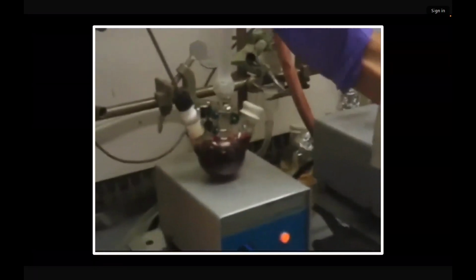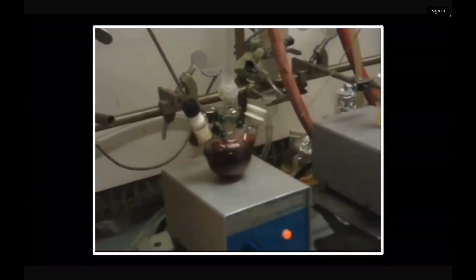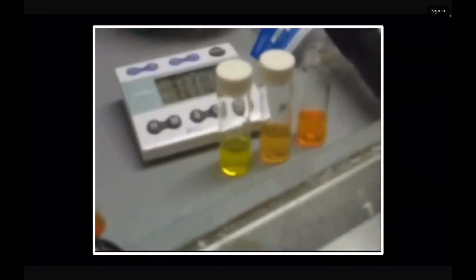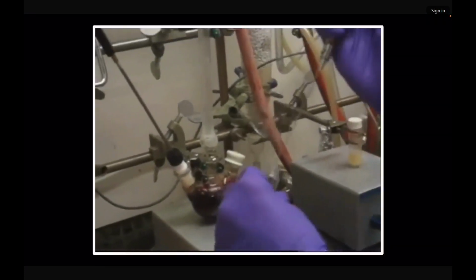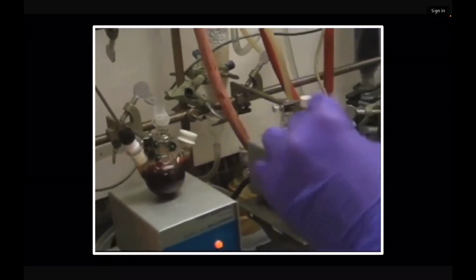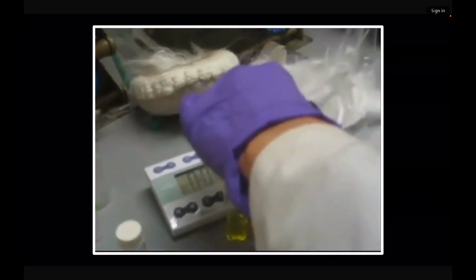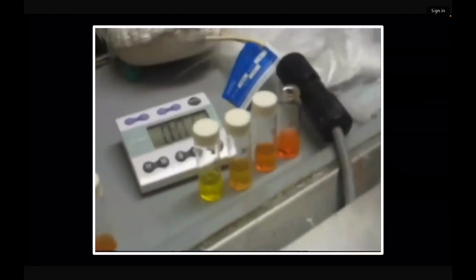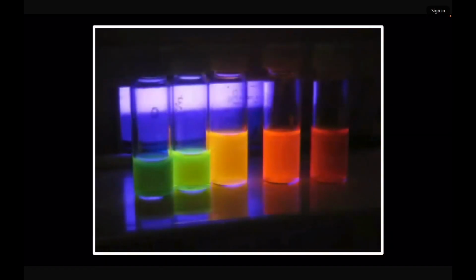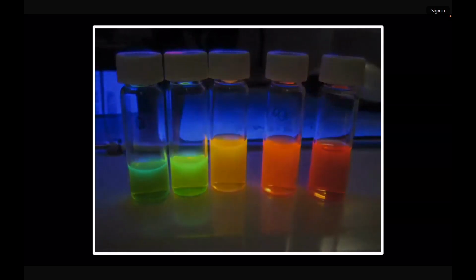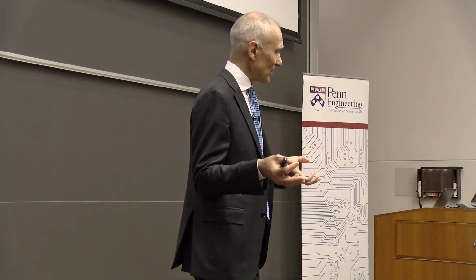And you can still take samples out. And you can see then the evolution of the growth of the material, keeping the size largely intact, based on the ideas from the 1950s of nucleation growth that physical chemist LaMer had talked about. And then you can turn on the UV light and see the fluorescence. The fluorescence of these materials, when we first did it, was on the order of 20%-ish. And I was so excited because these looked so bright to me. The reason why they looked so bright is because the samples I had made at Bell Labs had a quantum yield of 0%. So 20% is much bigger than 0%.